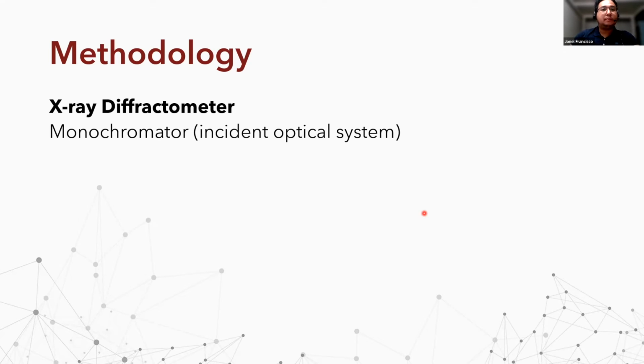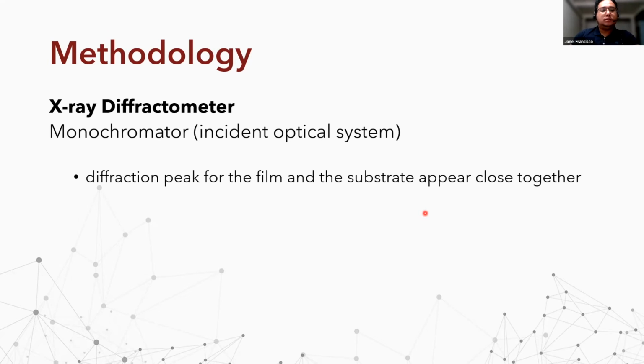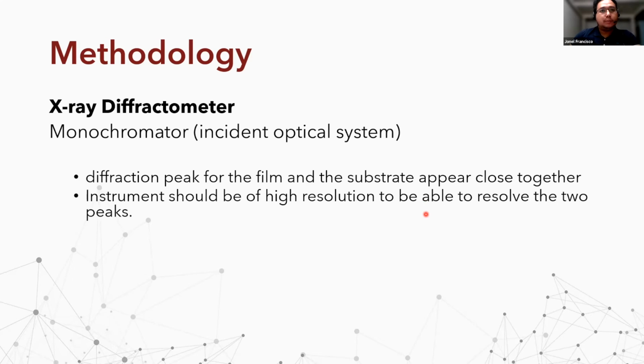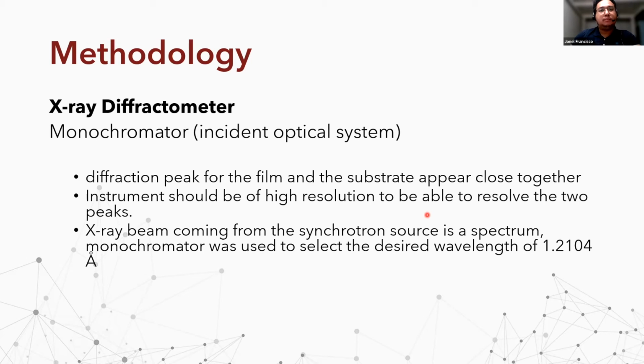For thin film XRD measurements, most of the time the diffraction peaks for the film and the substrate appear close together. Therefore, the instrument should be of high resolution to be able to resolve the two peaks. Also, the X-ray beam coming from the synchrotron source, as I have mentioned previously, is a continuous spectrum. Hence, a monochromator was used to select the desired wavelength of 1.2104 angstrom.